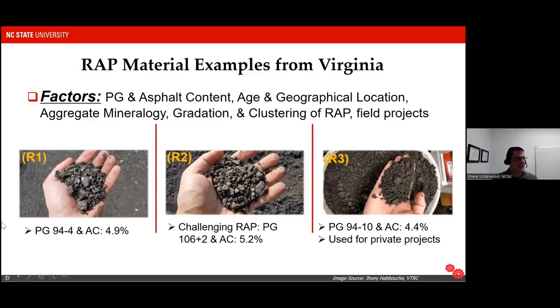You'll notice that they vary in terms of color, in terms of gradation. If we broke these apart, there would be different kinds of agglomerations inside. We also have different asphalt contents of these RAP materials, and those RAP materials have different binder grades. So even within one state, we can see variations in aggregate properties and asphalt binder properties. That will lead to inconsistencies in how the materials are used and how they perform in the field.